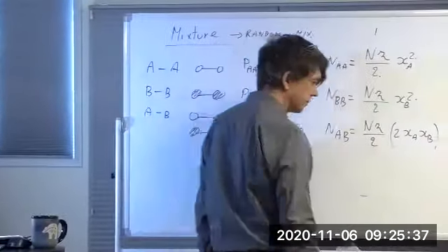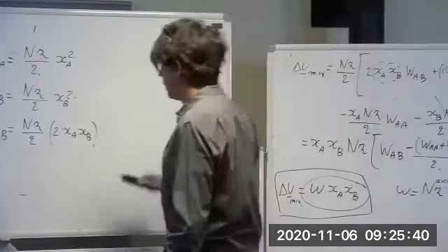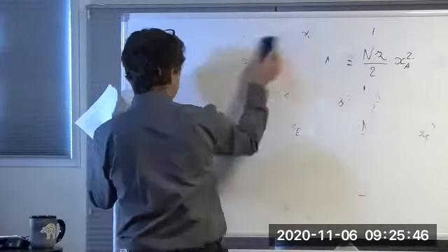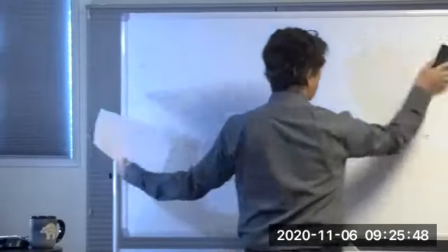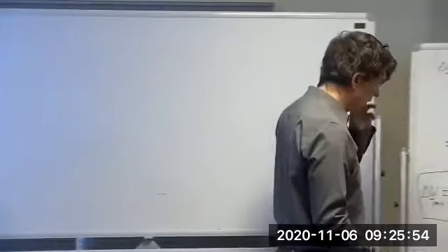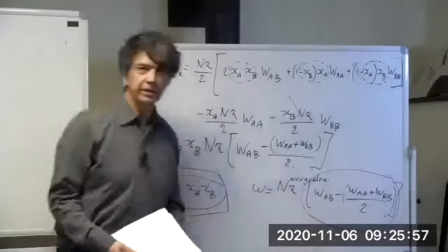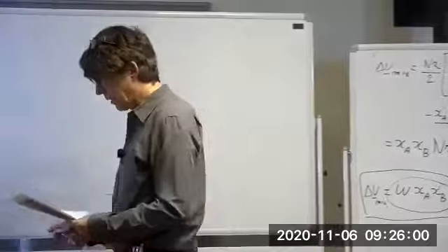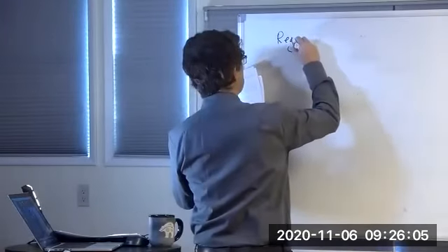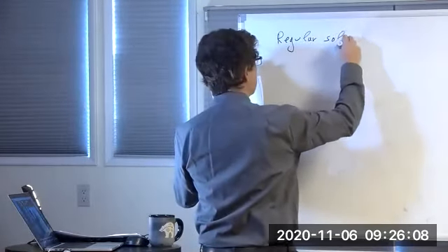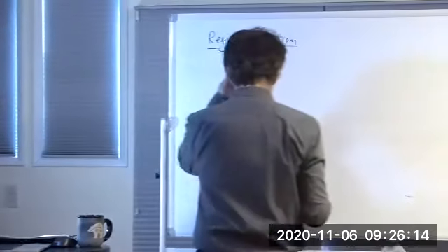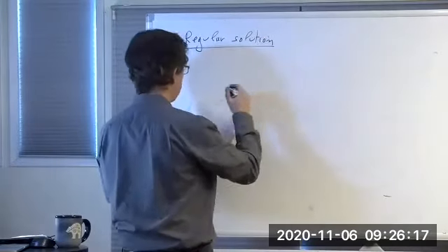So very often, people will call this the enthalpy of mixing and not the energy of mixing. Technically, it is just the energy of mixing, but since the P delta V term is very small, they are kind of the same, right? And so that leads us to the definition of what's called a regular solution. And again, this is an old thermodynamics name from old metallurgy, and there's nothing regular about a regular solution, but it's the name.